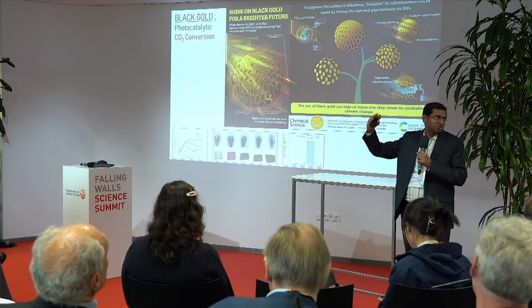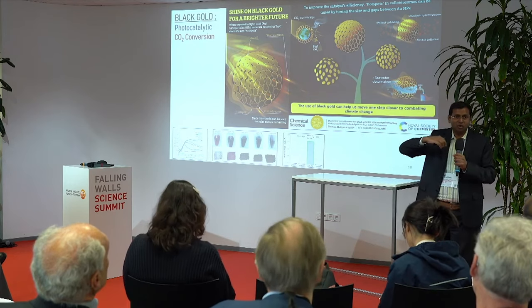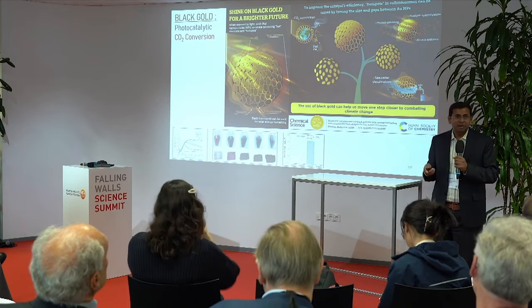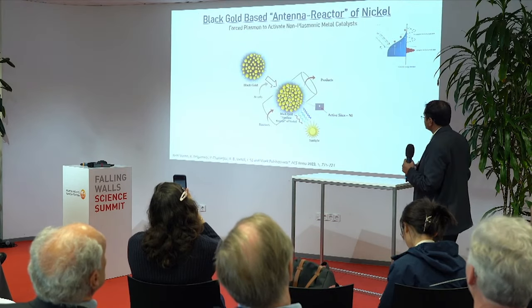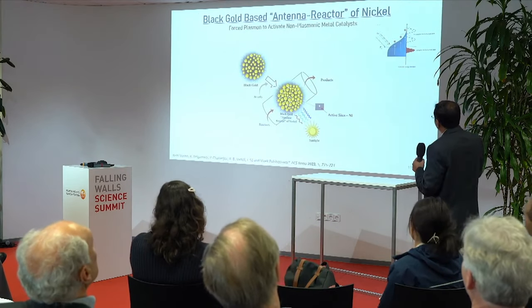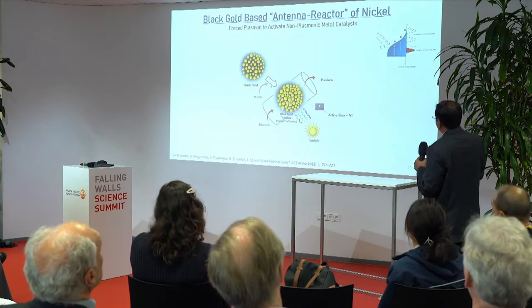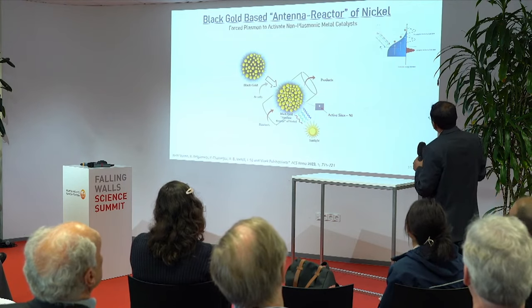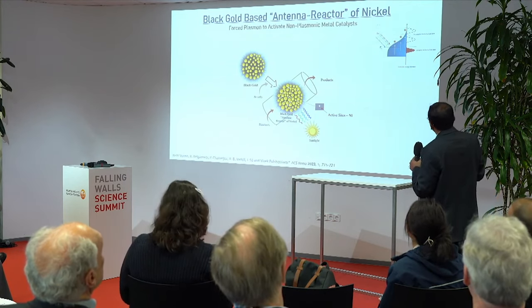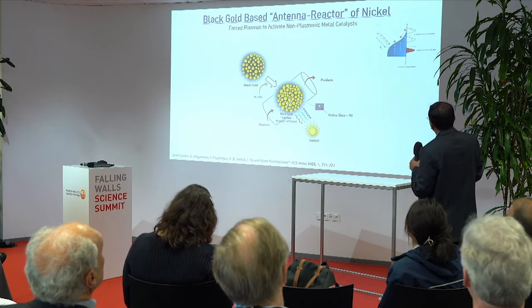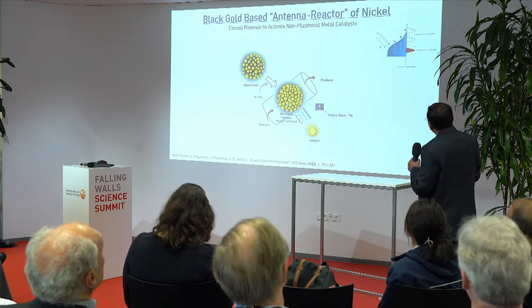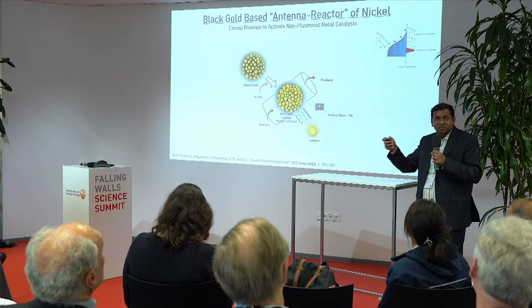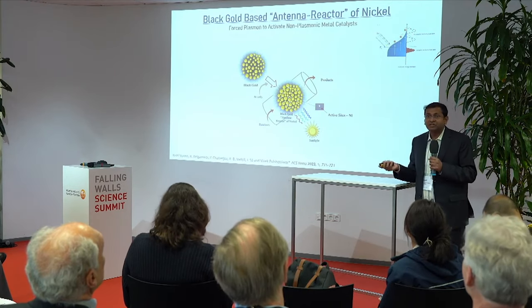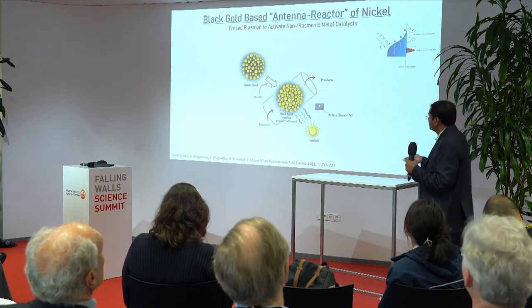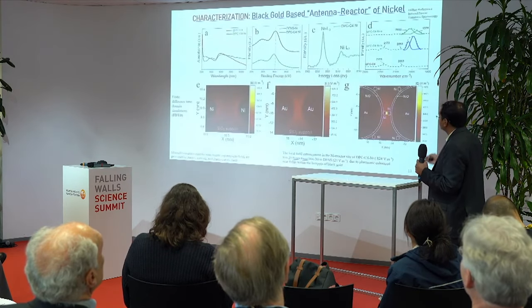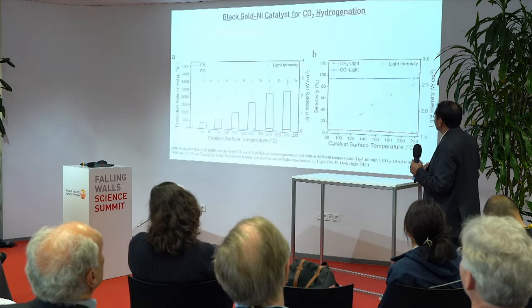Most of the time when the electron goes to the excited state, it will couple back with the hole and the electron cannot go to the CO2. So in order to solve that issue of lifetime, we came up with the idea that, okay, you are generating these hot electrons in black gold. You add one more material, say nickel, where the electron will move from gold to nickel. The electron is in a nickel state, and the hole is in a gold state. You're separating them, creating a heterojunction, and possibly that will have a better lifetime. We designed the catalyst like that, and I skip all of that. I will show you the activity directly.